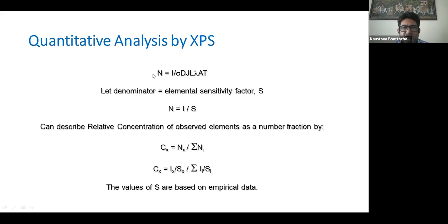If we take them overall as a sensitivity factor, the concentration of the particular element can be calculated from the intensity value. This gives us the parameter with which we can find the concentration of the elements present in the system. But with XPS, we should always understand that the concentration we are finding is the surface concentration of the element. We cannot say anything about the bulk concentration.